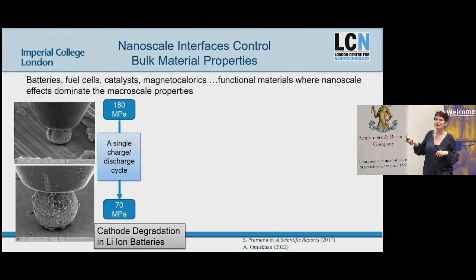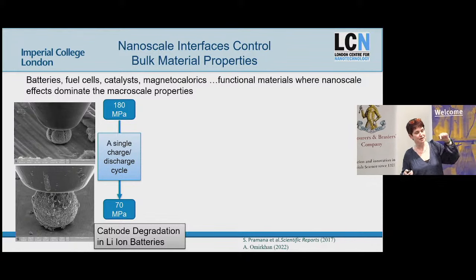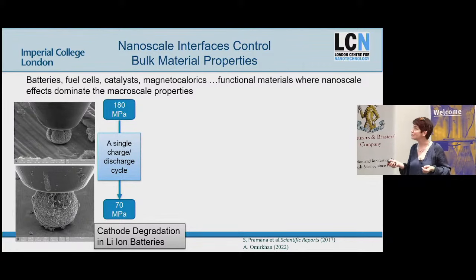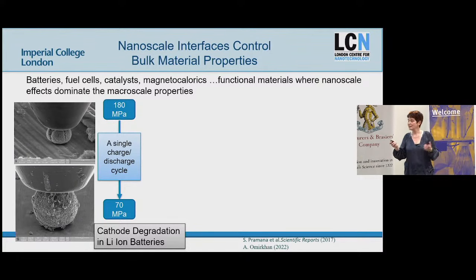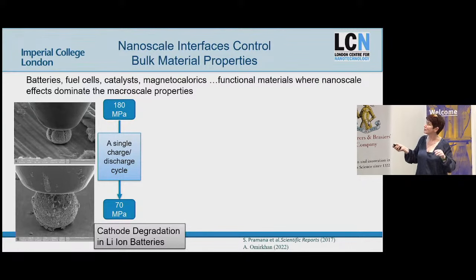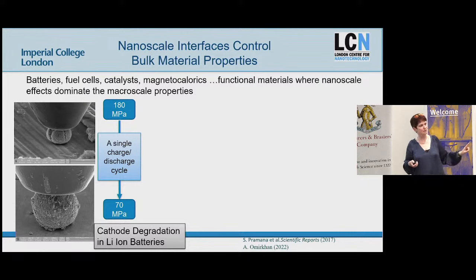This is, again, if you think about a human hair, less than a tenth of the size of a human hair, and we're making it and using it to crush the particle and measure the mechanical properties at the same time. And what you find is this process of intercalation in a battery, lithium ions coming in and out, in just a single cycle drops the strength of this material from about 180 megapascals down to about 70. A single cycle is enough to almost destroy the mechanical properties of this material.